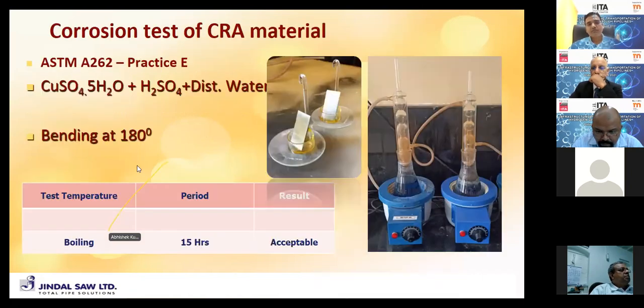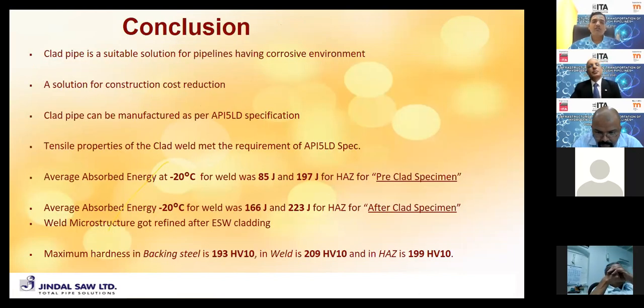Next. We conducted the corrosion test also as per ASTM practice E, where we have used copper sulfate and sulfuric acid solution, and we boiled it at a certain temperature for 15 hours, and after completion of that we bent it and found there are no cracks.